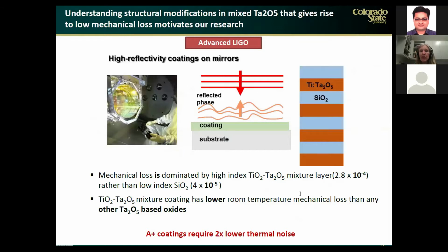As I mentioned earlier, the coatings for advanced LIGO presently use a high index layer, which is a mixture of tantala doped with titania, and a low index layer of silicon dioxide. This is the low index material, this is the high index material. And in order to make a reflecting structure, we stack about 30 pairs or more of this sequence.